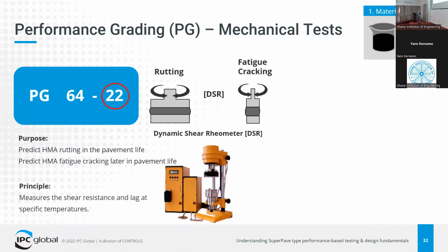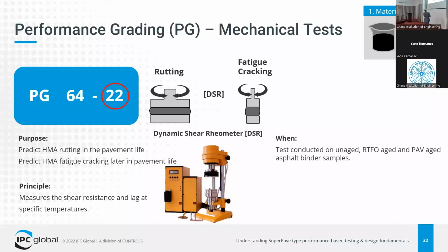It measures the shear resistance and lag at specific temperatures. It looks like a simple test. You have a very small disc, and you have a film of bitumen on it, and then another disc, so the bitumen is sandwiched between two discs, and the top disc is going to rotate very, very fast, and eventually we shear the bitumen through friction, and it will measure the shear resistance and the lag, so effectively the residual shear at a specific temperature. And the geniuses in the lab will use all that data to identify the shear and volumetric properties. And you conduct that test on unaged, short-term aged, and long-term aged asphalt samples, so that it's applicable at all the stages of the bitumen life.